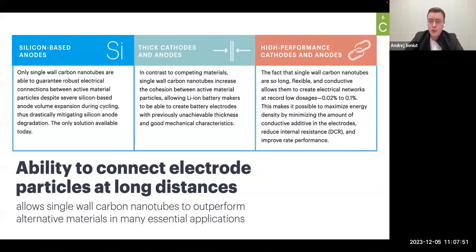and also assure uniform electrical conductivity throughout all the thickness of the electrode. And obviously the last application about which I will speak today is high performance cathodes and anodes. This is the application which requires you to max out everything from your cathode and anode. And the most conductive, the most durable, conductive and reinforcing materials such as single wall carbon nanotubes allow to do that: allow to achieve high discharge rates, allow to lower DCR, allow to use the record low dosage of single wall carbon nanotubes to assure the required battery resistance, etc. I'll show you a little bit more details about these applications over the course of my presentation. So let's start with silicon-containing anodes.